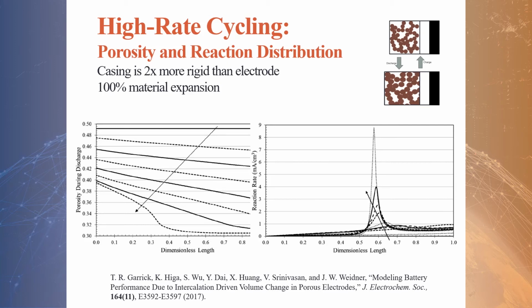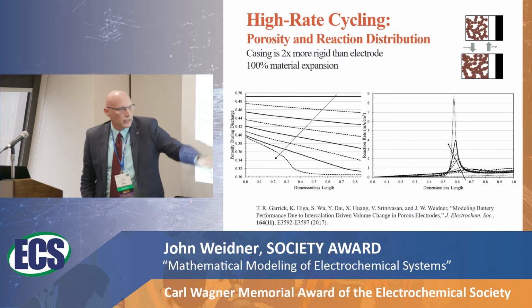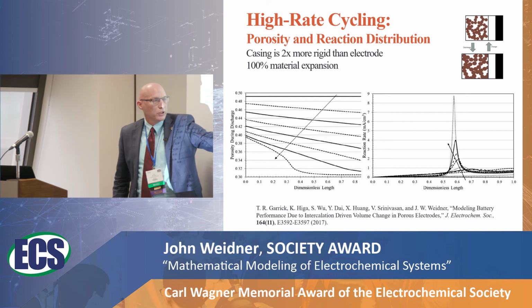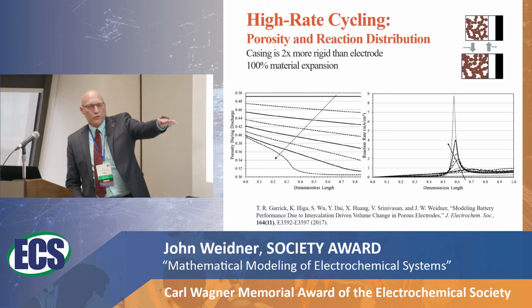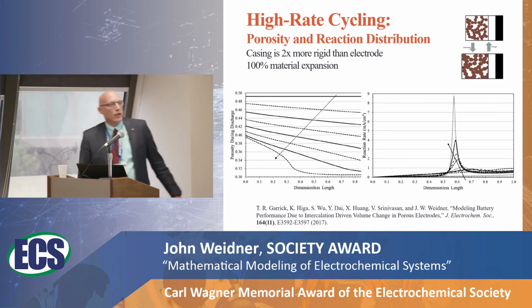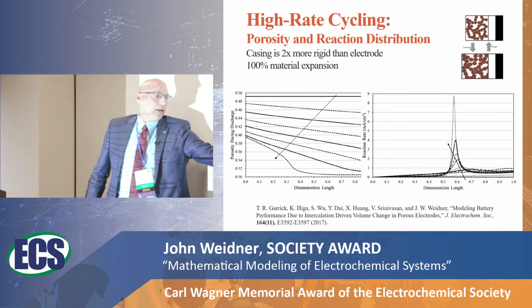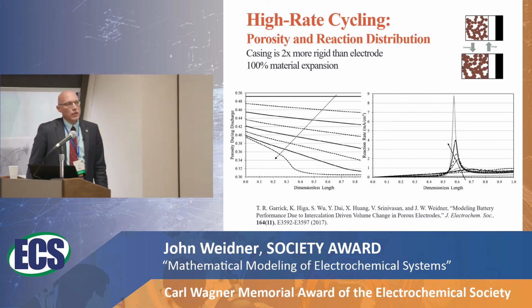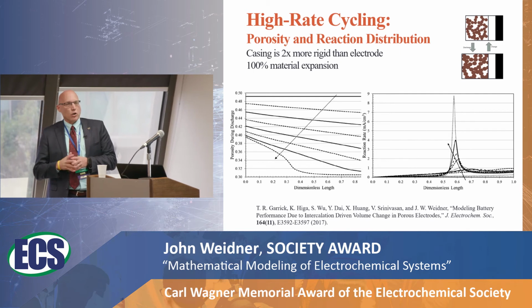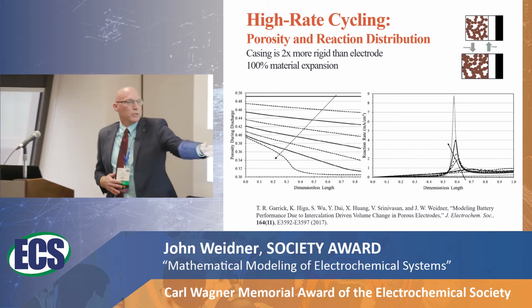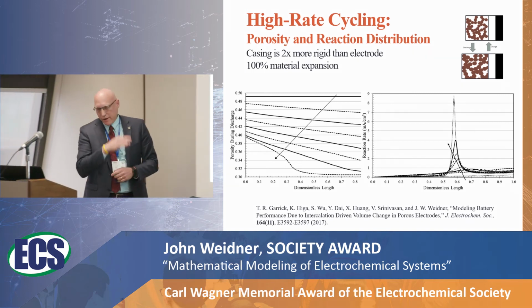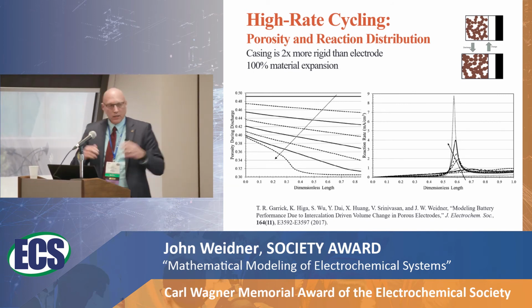Qualitatively, what we see in a lot of porous electrode battery modeling is, similar to the lithium thionyl chloride, the porosity is fairly constant in the beginning, then it gets more and more non-uniform, and then all of a sudden gets very non-uniform. If we look at the reaction distribution, it's not uniform, but it's fairly constant throughout. But once we've used up all the material in the front end, we get a wave front that moves through the electrode. That's a little different from the lithium thionyl chloride, which plugged the front. Here, we just run out of active material at the front, and then that wave moves farther and farther back until we hit the cutoff voltage.